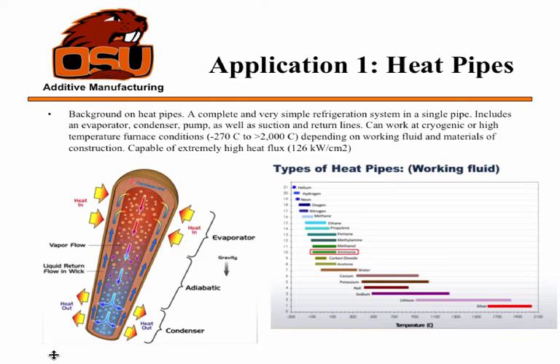They're also capable of incredibly high heat fluxes. This is generally at really high temperatures. They're capable of 126 kilowatts of heat transport per square centimeter of area. So ridiculously high. I think one really cool thing is they're used in isothermalizers, as they call them, in furnaces. They take a furnace which might have a couple of Kelvin differential and even it out to millikelvin variation in the entire furnace. And that's even at high sintering temperatures. So they use them in semiconductor processing and things like that for really tight parameter control.